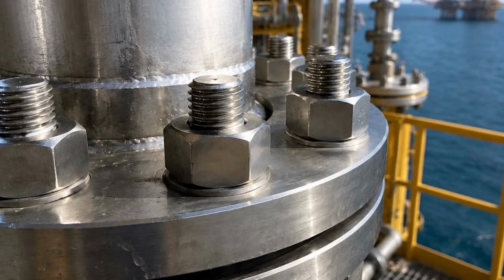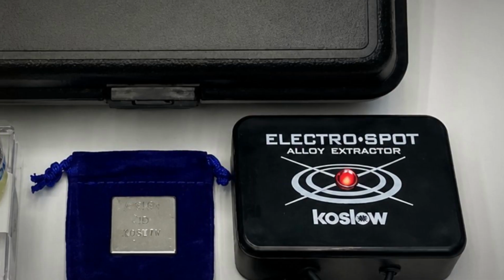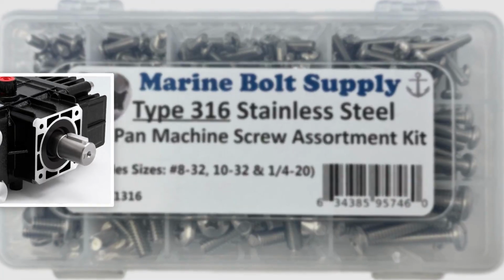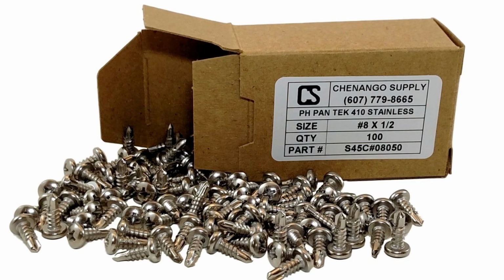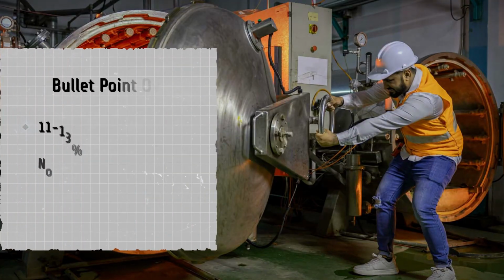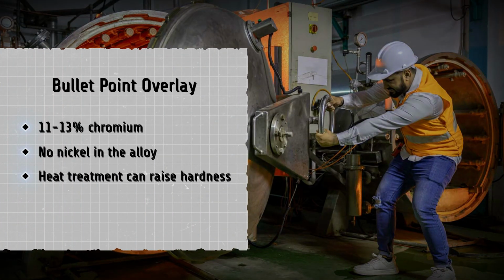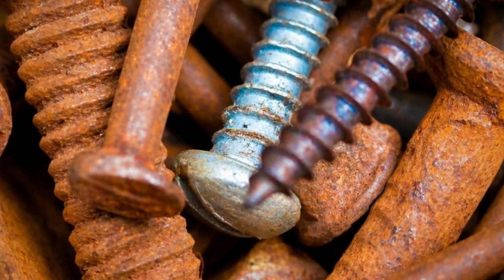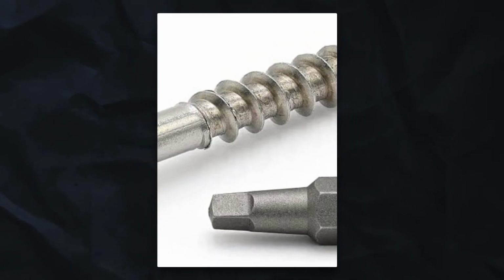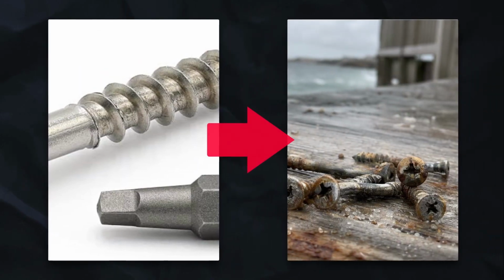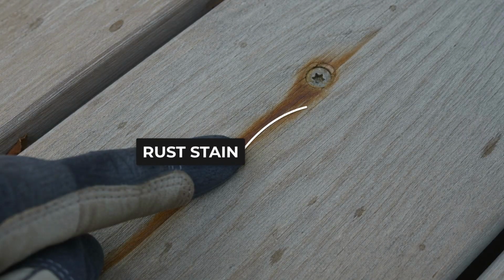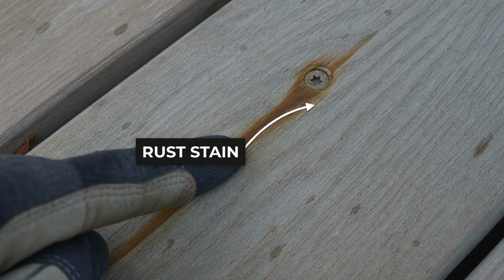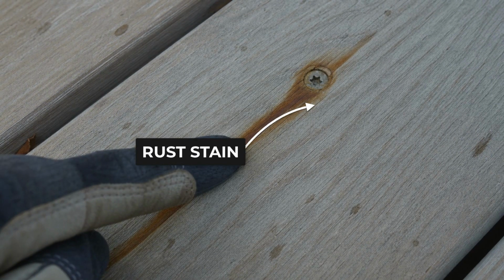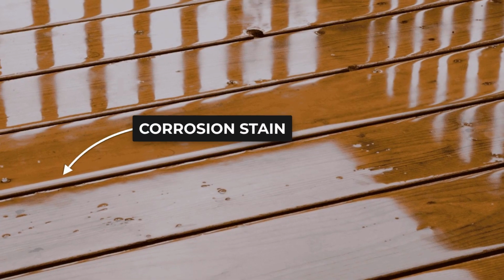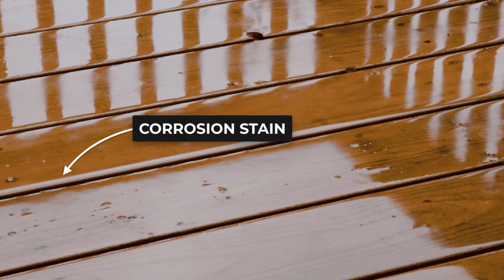Type 316 adds molybdenum. That single addition is what makes it the grade specified around saltwater, pool chemistry, and coastal air. Type 410 is the hard one: 11 to 13% chromium, no nickel at all, heat treatable, cheaper. The difference shows up in ways you can see. The 18 to 8 grades may pit and discolor in saltwater or other high chloride atmospheres, and when they do, the color bleeds through finishes and streaks the wood surrounding the fastener. That brown weeping down a cedar board is the screw failing in public.